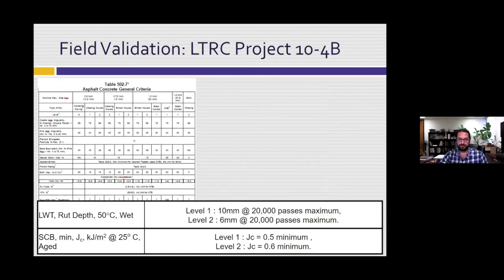Okay, so we landed on values of around 0.48 and 0.6 for where our triggers would occur based on the projects we looked at, and that resulted in our current 502.7 table, which is our asphalt mix design table, which has, again, for our different levels of traffic, the minimum cracking test criteria. And realizing that we have varying traffic levels for LWT testing, we varied those as well. So prior to this spec, all of our mixtures, regardless of traffic, were 6 millimeters at 20,000 passes. But realizing that with the increased asphalt content we may be seeing, plus this is an extremely rigid rut depth of 6 millimeters, we could afford a little bit more for our level 1 or our low traffic level mixtures.